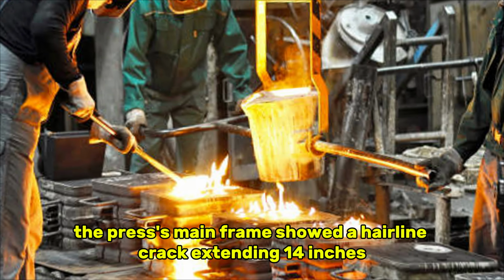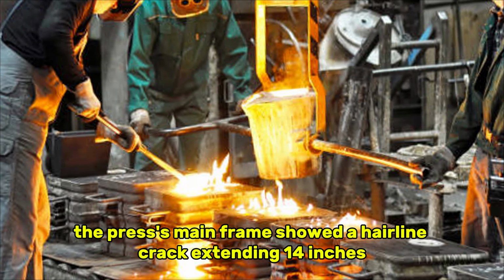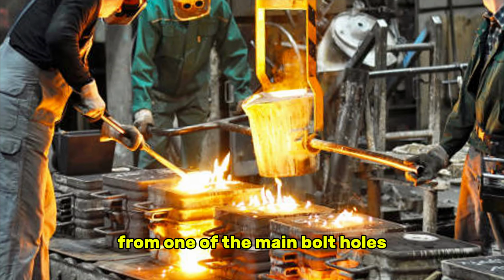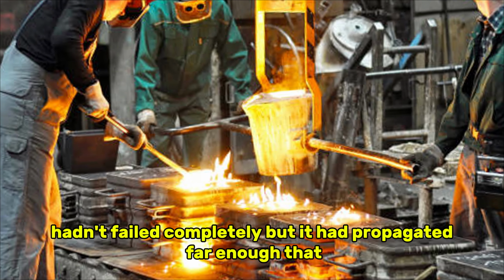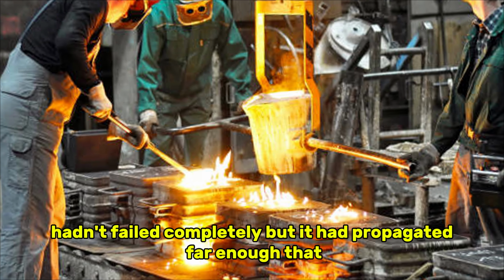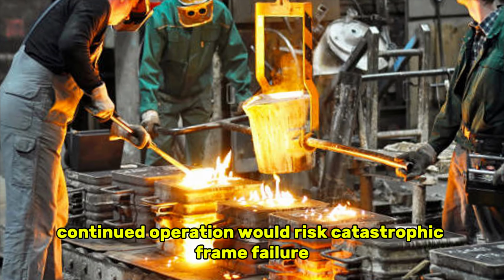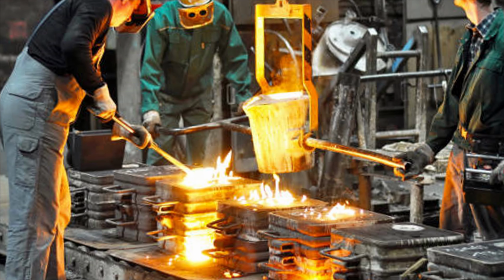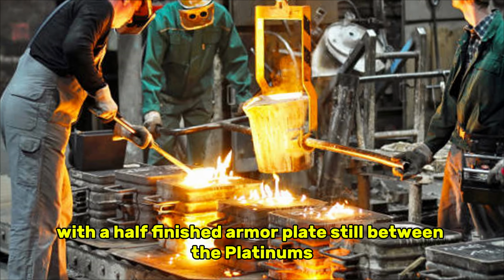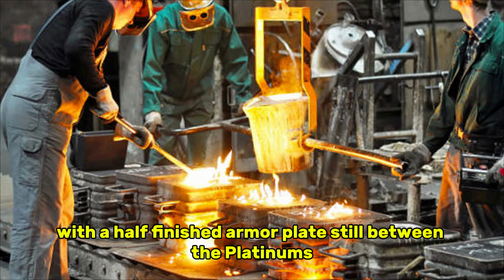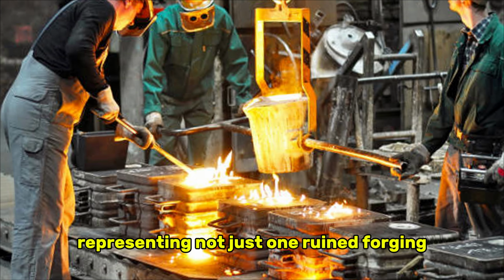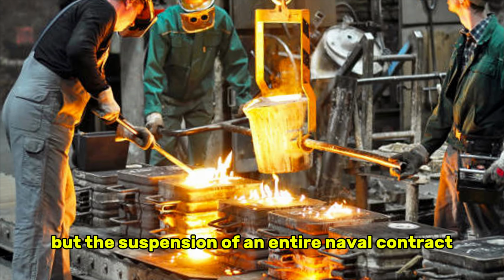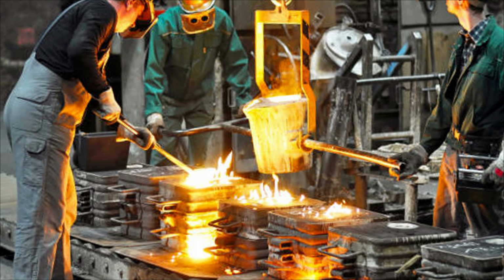The press's main frame showed a hairline crack extending 14 inches from one of the main bolt holes. The crack hadn't failed completely, but it had propagated far enough that continued operation would risk catastrophic frame failure. The press sat silent, with a half-finished armor plate still between the platens, representing not just one ruined forging, but the suspension of an entire naval contract.